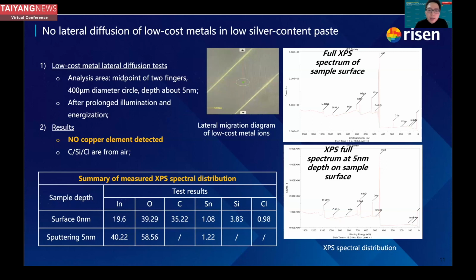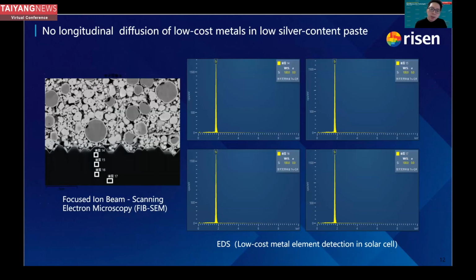As you can see, we selected a point between two fingers and the middle point of two fingers, in 400 micrometer diameter circles. We tested whether there was some penetration or diffusion of other elements within the paste. In the test, we can see only indium, oxygen, carbon, tin, silicon and chlorine were detected, but no copper was detected. So it verifies there is no diffusion in the horizontal direction in the paste. In another aspect, we also tested the vertical diffusion of the low-cost metal, which is copper. We selected a few points in depth under the fingers.